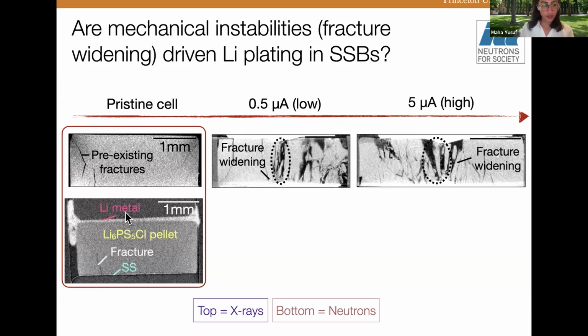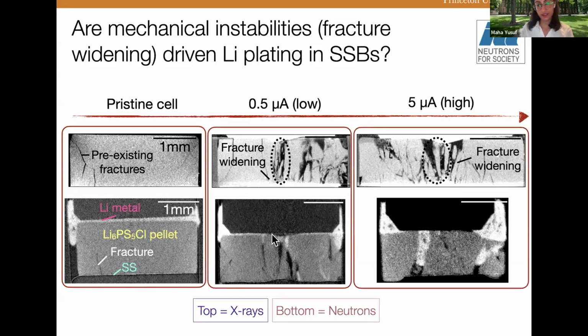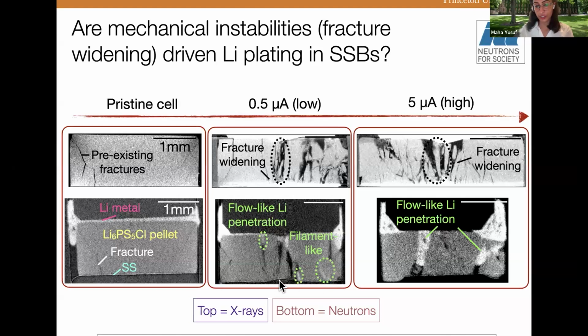So in the pristine cell, we can identify the current collector, the lithium metal electrode, and the solid-state electrolyte pellet. And now if you look at the images of the low and high current density, you can clearly see that lithium is penetrating these fractures and its behavior is different at the two current densities. For example, at low current density, I'm calling it filament-like lithium plating or deposition on this current collector, as compared to flow-like, where it's creeping through this giant fracture at a high current density.